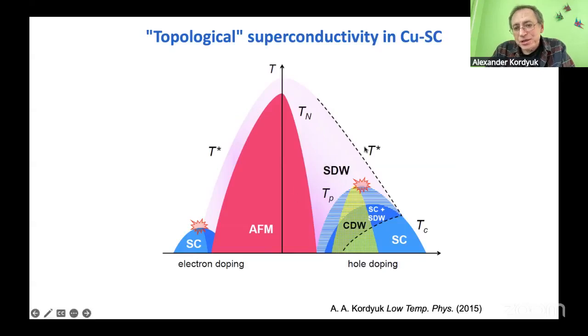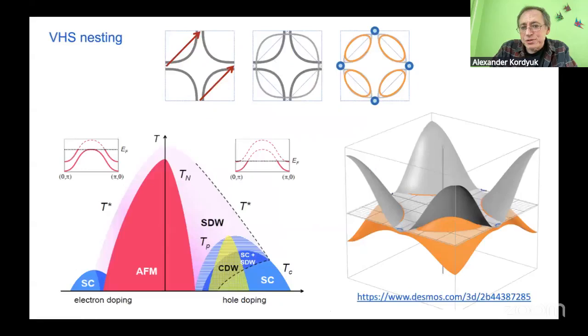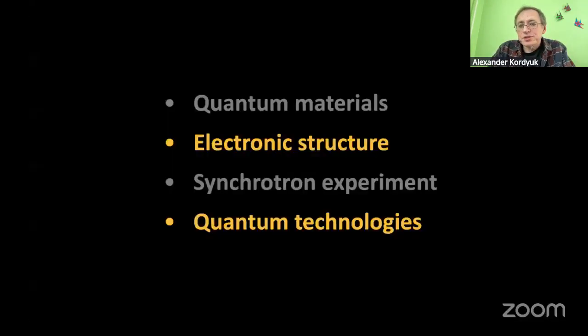But here we usually do not see it. It is the so-called pseudo-gap region, but it does not mean that there is no ordering here. It should be here, and it seems it is here, but it is just smeared out in reciprocal space. Taking it into account, we could expect that the situation in cuprates is also similar, that we need to understand this mechanism of enhancement of superconductivity with these small Fermi surfaces. But this work is still not finished.